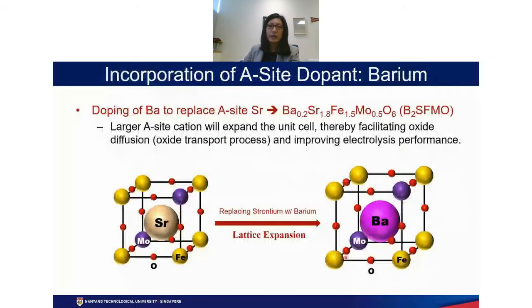So what we are thinking of doing is trying to see if we can make it even better by doping its A site. The A site is strontium, and if we replace some part of the strontium by doping with barium, then we can induce some lattice expansion. This barium is larger than the strontium, so this larger A site cation will expand the unit cell. So it's likely that it can facilitate the oxide diffusion within the electrode, and also improve the electrolysis performance. So that's the idea.